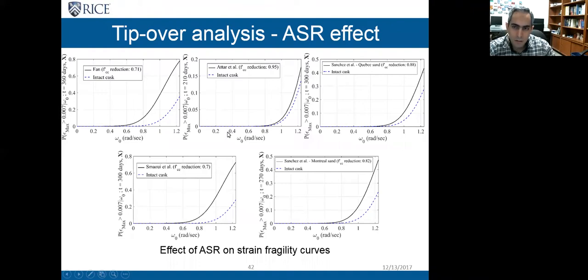And as we see, in all cases the probability of failure increases for the ASR affected casks. And in the cases where the reduction in the initial compressive strength was larger, larger increases are observed. For example, in the worst case, which is the bottom left figure, the reduction was about 30% in the compressive strength. And at the end of the test, the compressive strength was about 70% of its initial value. And as we see, we have the larger jump in the probability of failure.